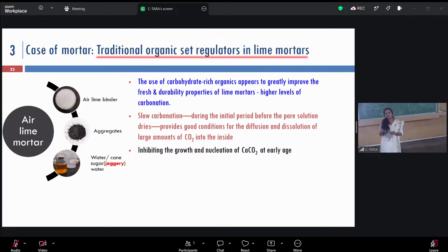But now we don't have time to wait for 1 year for your structure to get strengthened, so we don't use lime anymore in newer structures. So anything that gives extra CO2 to the material would ideally enhance the process. That's why people were using urad dal, different kinds of dal and fruits, fermented. So one is jaggery. And here we wanted to explore, can we standardize using jaggery, which is sucrose, cane sugar, in some way to say that this is the dosage, this is how you should use it so that you get an excellent lime-based binder.